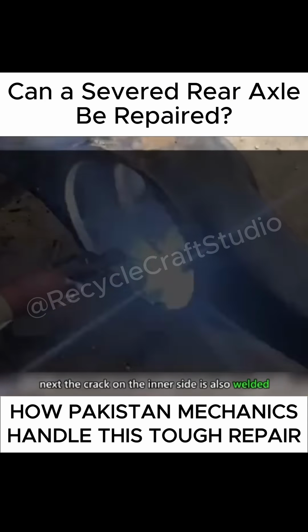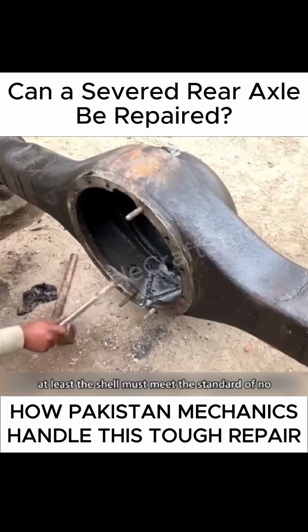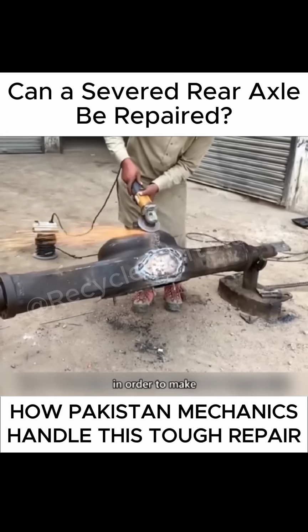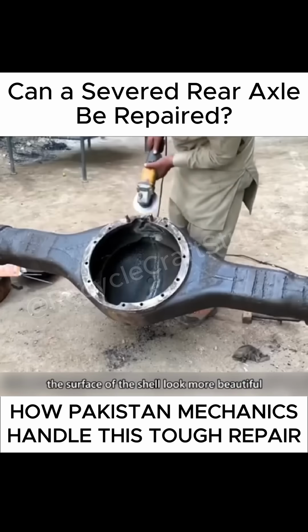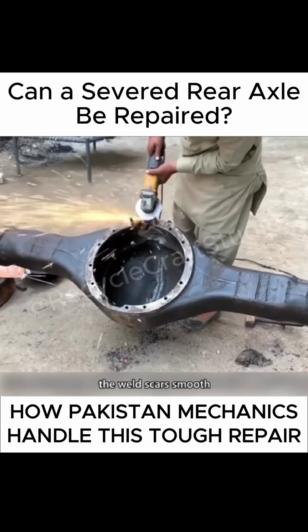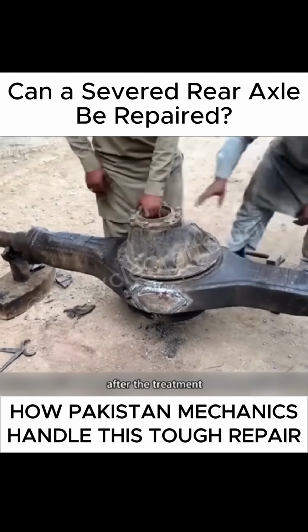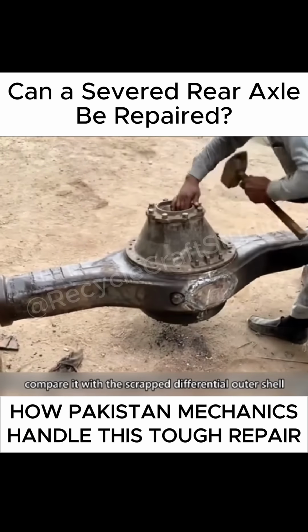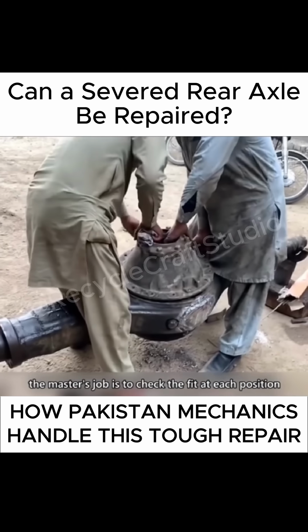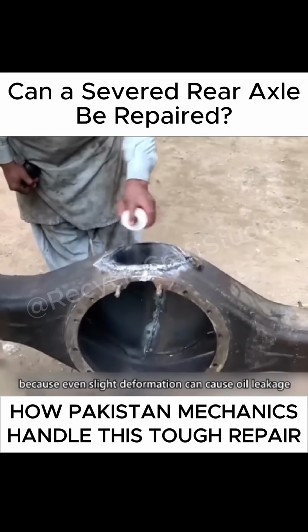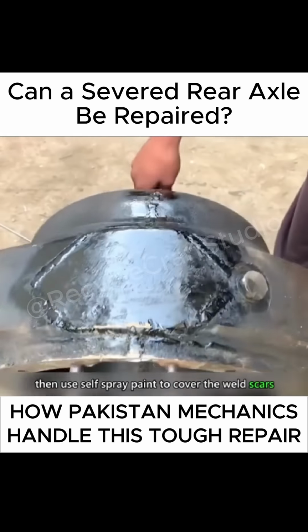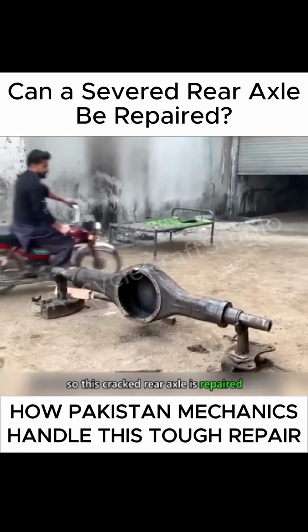Next, the crack on the inner side is also welded. At least, the shell must meet the standard of no oil leakage. In order to make the surface of the shell look more beautiful, the master also needs to use an angle grinder to grind the weld scars smooth. After the treatment, compare it with the scrapped differential outer shell. The master's job is to check the fit at each position because even slight deformation can cause oil leakage. Then, use self-spray paint to cover the weld scars. So, this cracked rear axle is repaired.